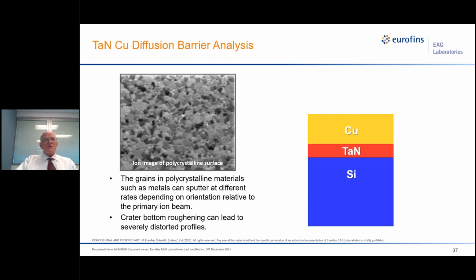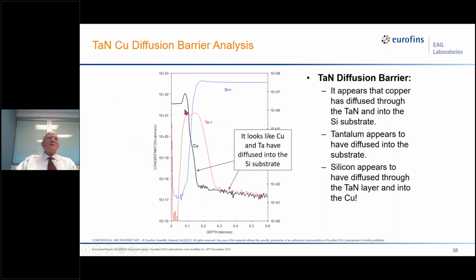And here is the killer of killer samples, where you have to sputter through a polycrystalline layer, and you're trying to see if the copper gets through to the silicon. If you analyze from the front, you get very bad roughening of the sample. So the surface is simultaneously in the copper and in the tantalum nitride. And as the sputtering continues, it will be really bad. So the copper here, it looks like it's gone into the silicon, but you have to ask, has it really? In this particular analysis, these are artifacts.